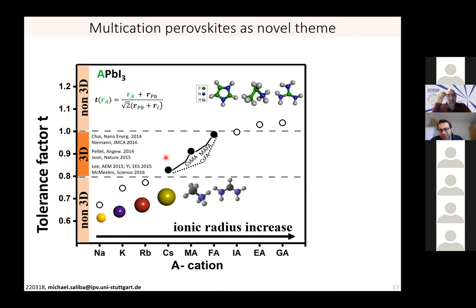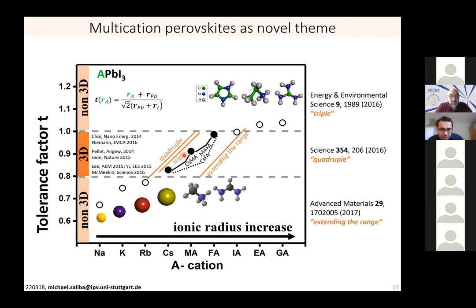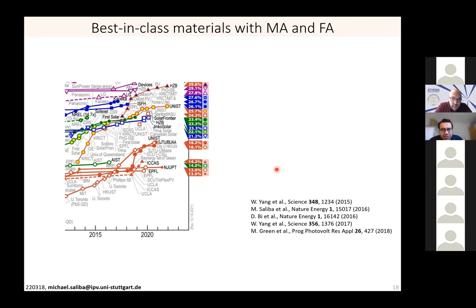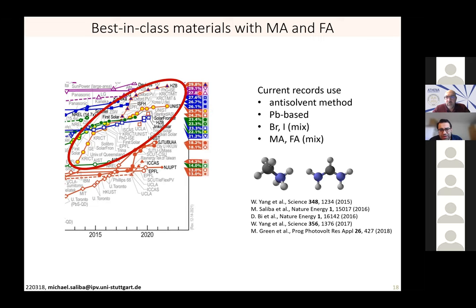And you see here, the way to get around this is to start mixing them, to get an effective cation radius by using two of the species. So this was done for a long time. And then by starting to mix these in a systematic way, this will be the big theme for this segment of the talk. You see it here. One thing we've done in terms of research was to mix the three existing ones together, motivated by these double cation perovskites, but then also to look at smaller or larger cations to be included in very small quantities within this material. And just to give you an idea, these are the most recent ones. As you can see, it's very close to 30% now. It's only a question of time until this goes further.